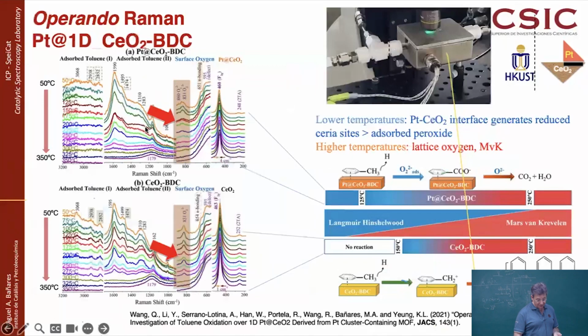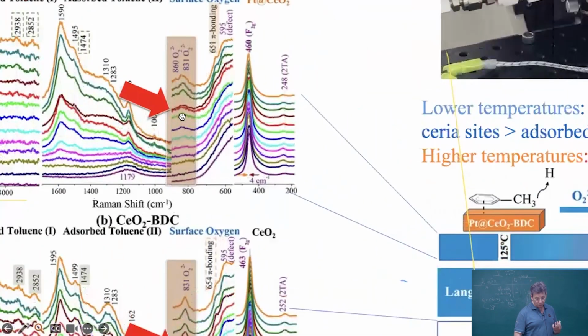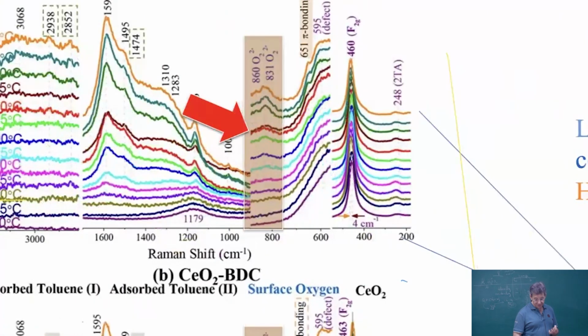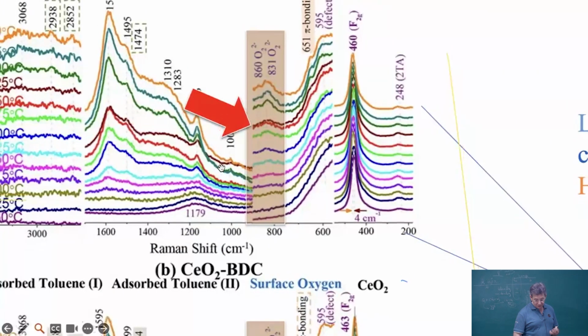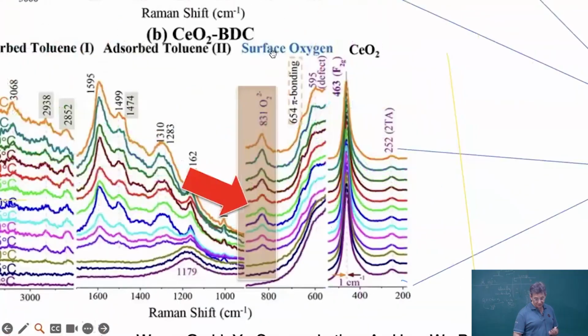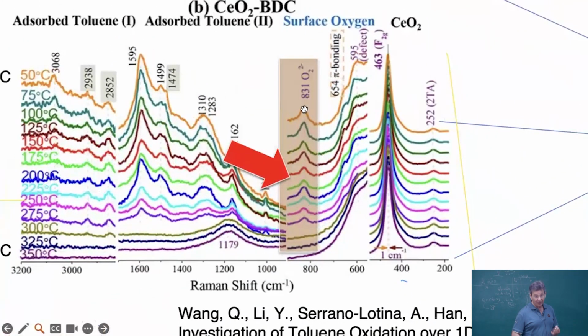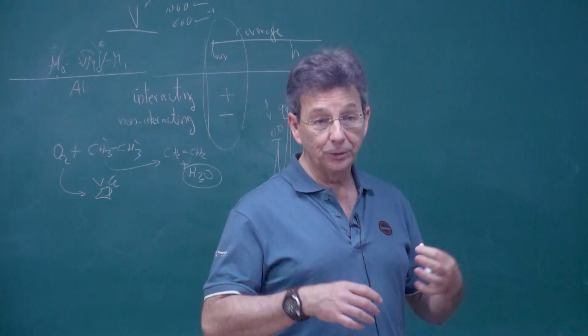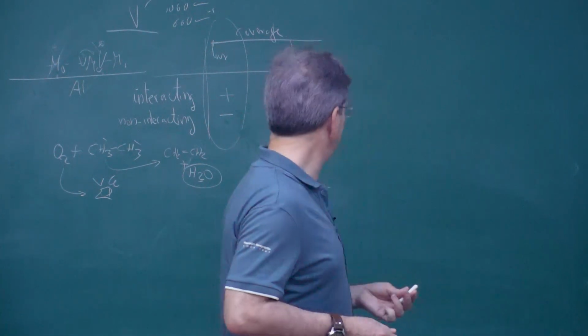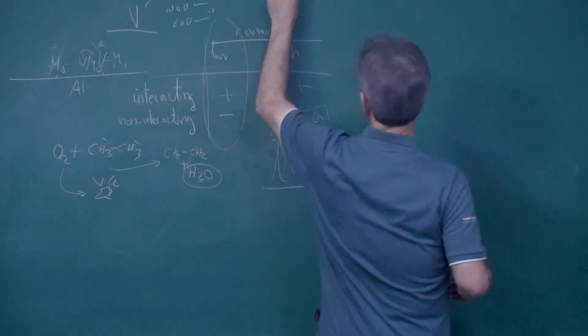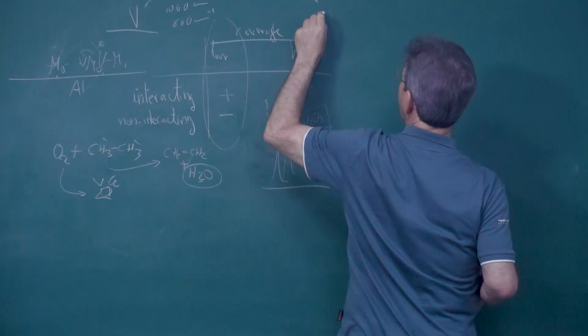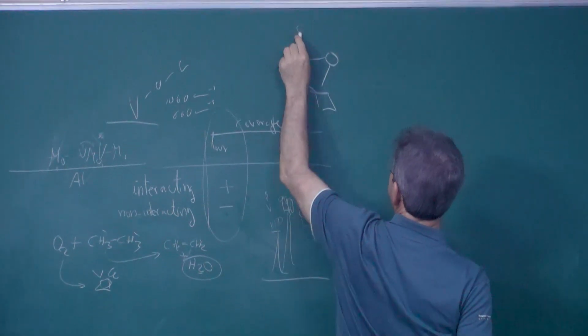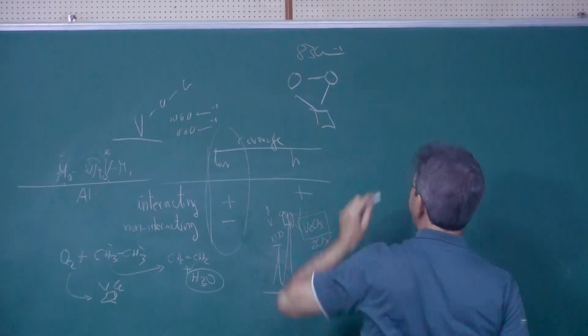Operando Raman studies again show us a big amount of hydrocarbon species at the surface. As you increase temperature, you get rid of them. But the most interesting part is when it comes to the oxygen species, the peroxide species. So you can see that in the case of ceria nanorods that derive from benzene dicarboxylate, basically you have this vibration at about 830, which is typical of peroxides sitting on a given site. So this is like 830 wave number.